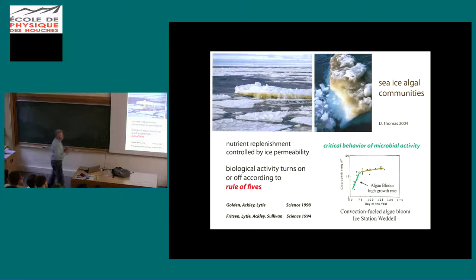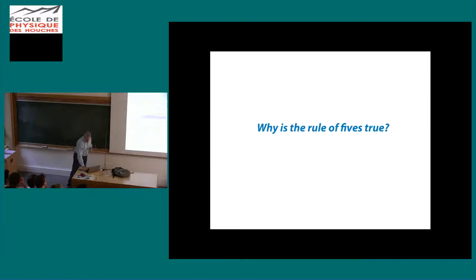So this is actually showing how dramatic this rule of fives can control biological activity. This is an algal bloom that just got shut down, and that 2-day period is where the critical isotherm, below which you're impermeable and above which you're permeable, passed through the layer where the algae was living. So it's rather dramatic, the effect that this rule of fives can have even on the biology.